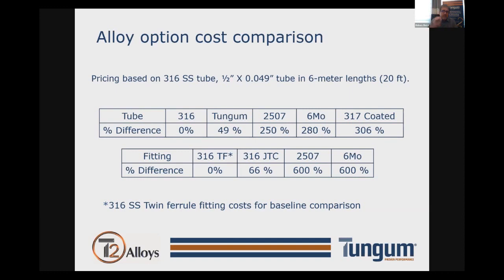With respect to 2507 and 6 moly, the added benefit actually is not significant enough to merit the cost, because even with these two alloys, although you do get an increase in corrosion resistance, the increase only lasts you say anywhere between 8 to 12 years before a crevice corrosion failure. And this is what we've been told in the industry, is that 2507 and super duplex alloys typically fail with respect to crevice and not pitting.